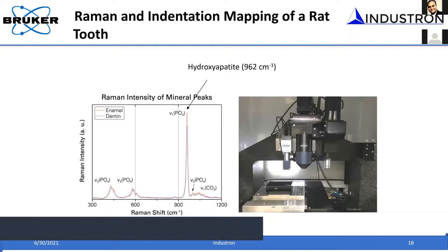This is what I'm going to show in this particular slide, where this has been done for a rat tooth. What we have done is take a tooth material, cut and polish it, and put it on nanoindentation. This is a typical 950 or 980 nanoindenter. Along with this nanoindentation, if you look at this arrangement, you have a low load transducer, a high load transducer, and then an optical microscope. In that optical microscope, you can combine Raman so that we can use it as a Raman microscope.